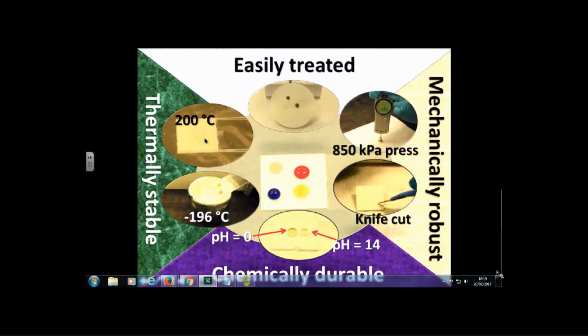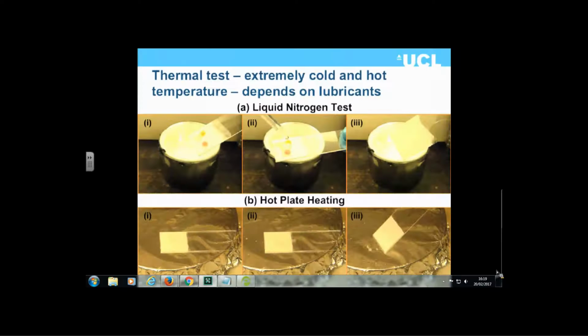You can heat them up to 200 degrees C and they still work. You can leave them for 3 or 4 months and they still work. Eventually, over long time periods, the lubricants will evaporate, but the lubricants we've got tend to stick to the surfaces for a huge amount of time. The surfaces themselves are also very resistant to both acid and alkali, able to withstand pH 0 or pH 14 for fairly long periods before they show any degradation.